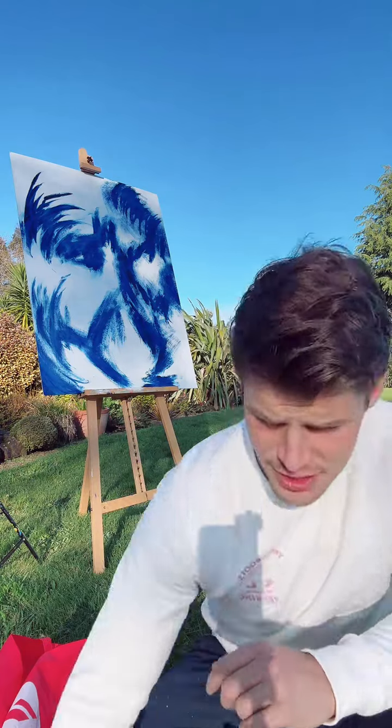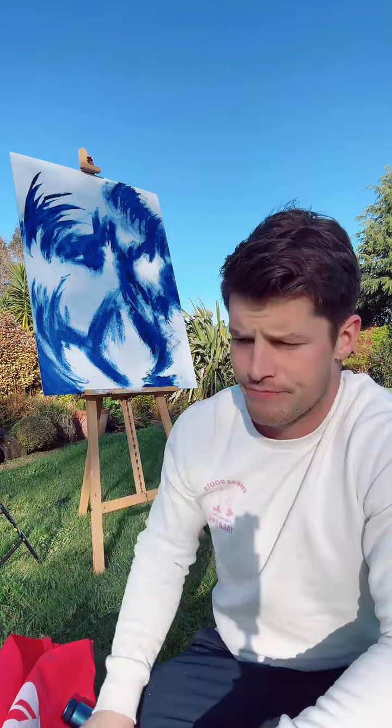regular off-the-shelf varnishes. Just give the acrylic painting time to fully cure. Touch dry isn't enough. It needs to fully cure. So if it's a thin layer, a couple of weeks should be fine. If you're doing really thick acrylic paintings, you've got to let that painting dry the whole way through. Otherwise, when you put the varnish on, moisture is going to get trapped between the varnish and the paint. And if moisture gets stuck under there, that's a recipe for disaster for long-term archiving.